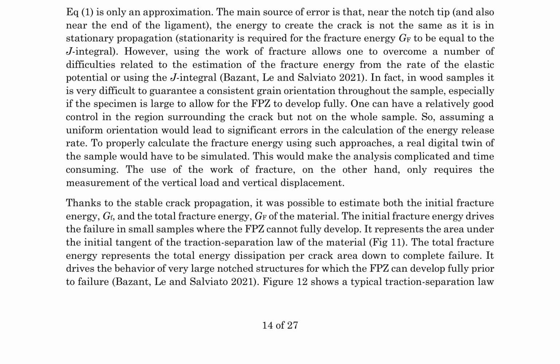The authors demonstrate the estimation of both initial fracture energy, G_f, and total fracture energy, G_F, of the material. Initial fracture energy drives failure in small samples where the fracture process zone, FPZ, cannot fully develop, whereas total fracture energy represents the total energy dissipation per crack area down to complete failure. A visual representation of the traction separation law of the material is provided, showcasing the initial and total fracture energies.